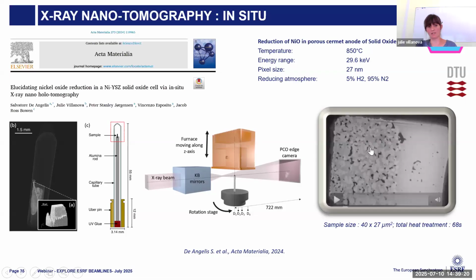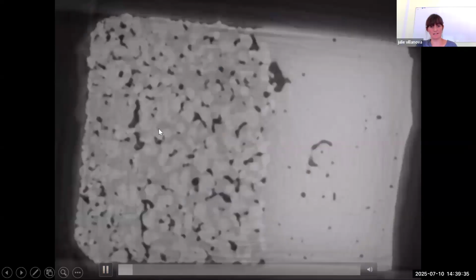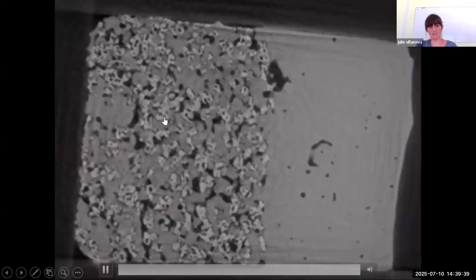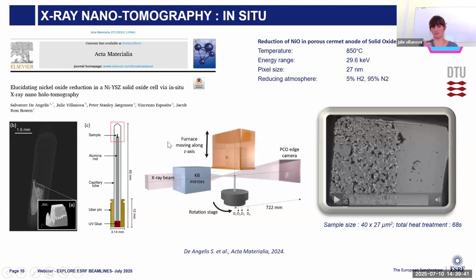So this is a solid oxide cell. Here we have the electrolyte in gray. So this is zirconia. You have zirconia, all those particles in gray. The dark parts are pores. And then in bright white, you have the nickel oxide. This nickel oxide will react and will reduce, creating nanoporosity. And after that you have a coarsening of this metallic nickel.